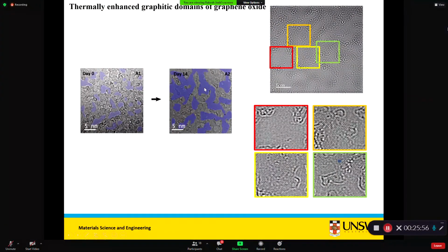So the blue ones are the large graphitic domains, and here we also did HRTEM characterization. So see, these are large graphitic domains here. These are large graphitic domains here. These are the mixed ones, but still we need to do more work in this direction to make it very large. If we can make highly reduced graphene oxide, or even if we don't change the functional groups, if we can have higher graphitic domains, this will have an advantage.